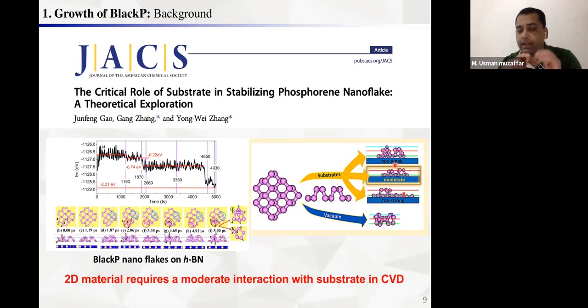He concluded that if someone wants to grow a 2D material on a substrate, the interaction between them should be in a moderate regime. Too weak, too strong, not good. The moderate regime should be a suitable candidate in CVD, the chemical vapor deposition technique. So growing black phosphorene on a suitable substrate is still a daunting challenge in the growth field.